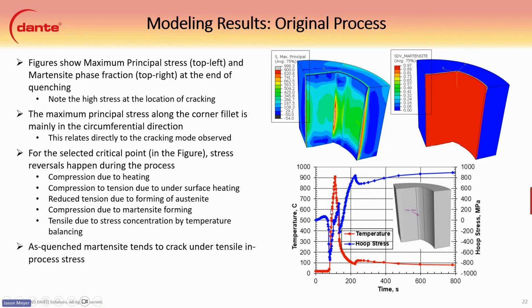We show the temperature history here, where it starts off at room temperature, and then it spikes up to about 900 degrees on the surface and the corner here, and then it drops down and quenches to martensite, and then there's an eventual air cooling afterwards to get to room temperature. And so again, just like we saw with the induction stuff, we have a compression here due to heating, and then as it's balancing out, it goes back up to tension. You can see that the residual stress gets to about 650 MPa and then transforms to martensite, and you can see the compression that's formed from that transformation.